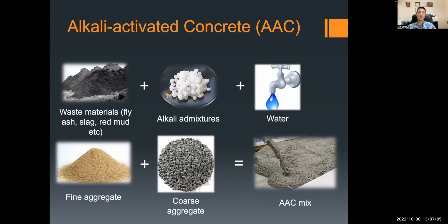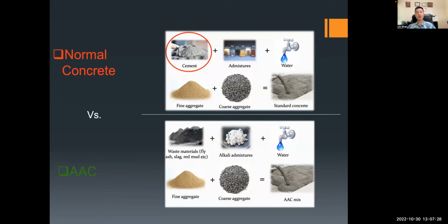So AAC, or alkali-activated concrete, uses waste materials such as fly ash, slag, and red mud, plus a small amount of admixtures, we call that alkali-activated admixtures, plus water, sand, and coarse aggregate mixed together, we have concrete. Comparing normal concrete and AAC, both use water, sand, and coarse aggregate. They all need a small amount of admixtures. The major difference is AAC uses waste materials instead of Portland cement.